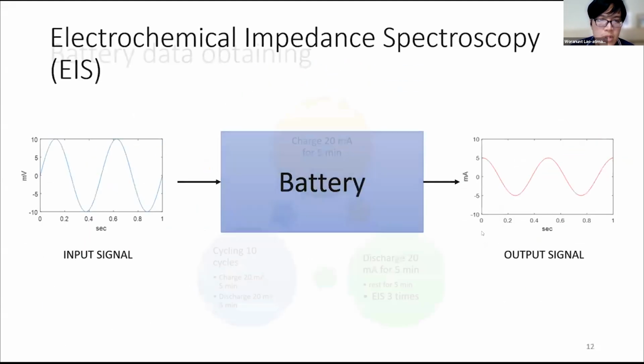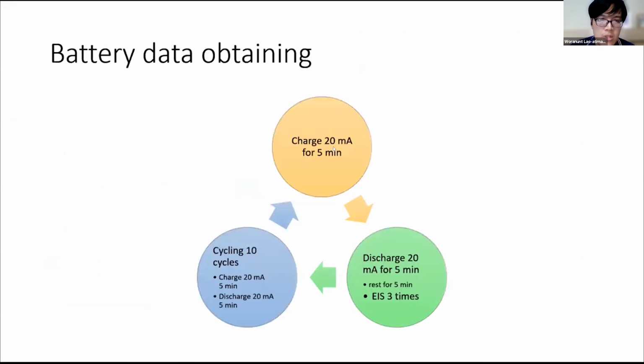The rest time between cycles: I charge at 20 milliamps for 5 minutes, discharge for 5 minutes, and then rest for 5 minutes. And then I test EIS. But when I cycle for another 10 cycles, I don't have the rest period in the cycling.